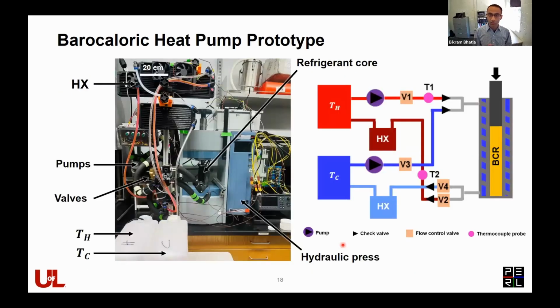and barocaloric core. So this is the actual assembly that we have for the barocaloric heat pump in our lab. It basically comprises two constant temperature thermal reservoirs for testing. We have solenoid valves and peristaltic pumps that basically pump ethylene glycol at high and low temperatures through the barocaloric core. And we also have thermocouples at the entrance and the exit of the barocaloric core to measure the inlet and outlet temperatures. Everything is controlled by a DAC, and so we can time the cycles pretty well. We also have heat exchangers to mimic the heat load, heat being released to the hot side and heat being absorbed from the cold side.